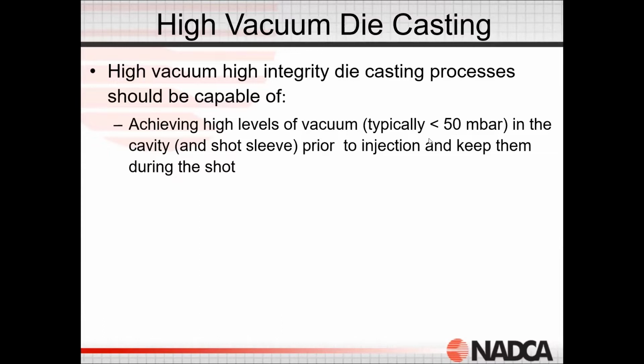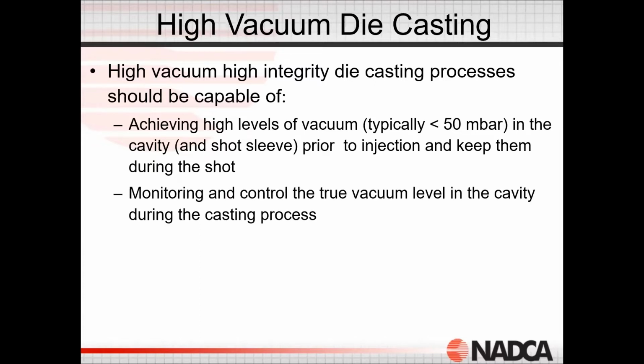With that kind of vacuum draw, we're eliminating a lot of the air inside the system. We've got to be able to monitor that in real time. When you're making a die casting, you're injecting the aluminum at high velocity. You can fill a casting, whether it's 2 pounds or 75 or 80 pounds, in a time frame of about 49 milliseconds to about 90 to 100 milliseconds. So in 0.1 seconds, we're filling a 70-pound die casting. That injection speed is very rapid, and solidification takes place very rapidly.